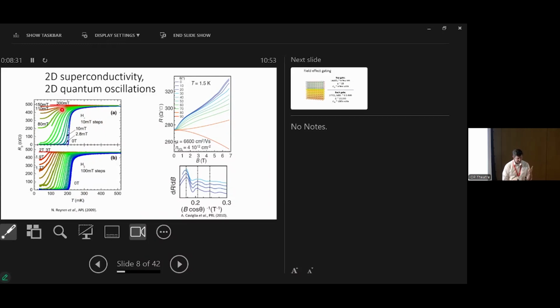Okay, so it's a two-dimensional superconductor, but it also showed quantum oscillations at higher magnetic fields. I won't go into the details of this. They're not incredibly convincing oscillations, but they're there and could be shown to be two-dimensional as well. And this actually was only probably the second time. We'd done some studies in a slightly related system a few years earlier, but this was only the second time where these two phenomena had been seen in the same material system. So that was already quite interesting, that we can have a two-dimensional material in two senses of two-dimensional superconductivity, and the Fermi surface was two-dimensional as well.